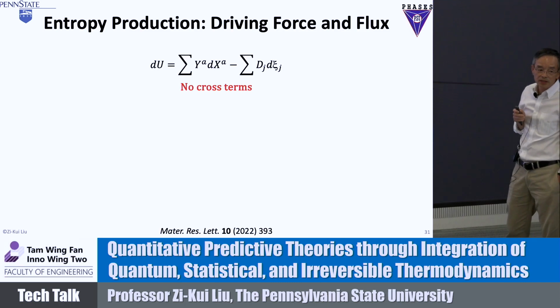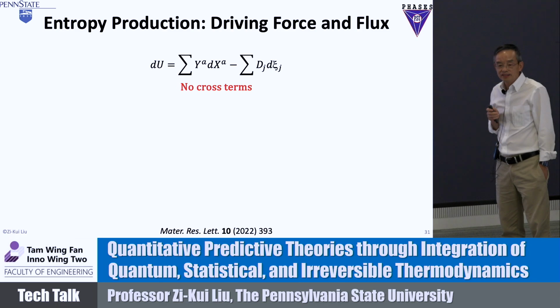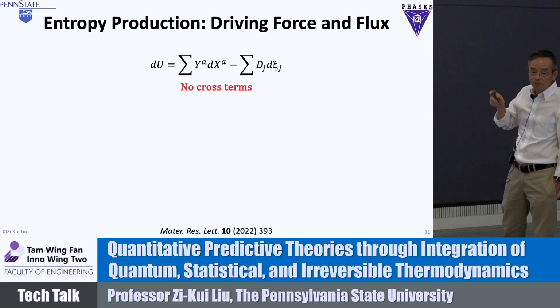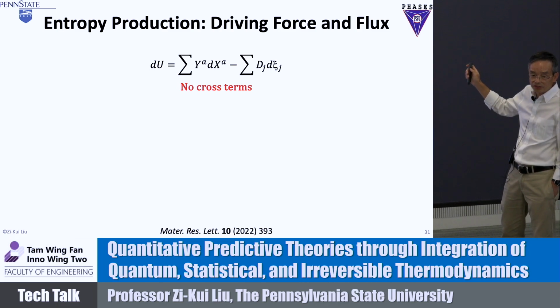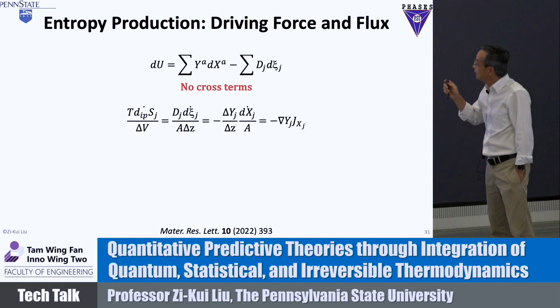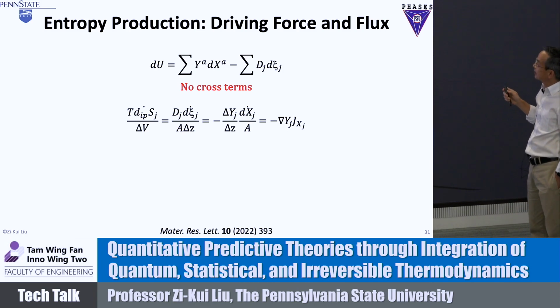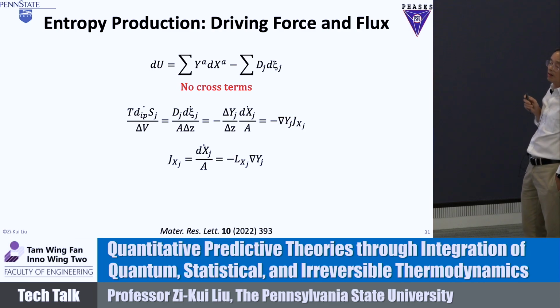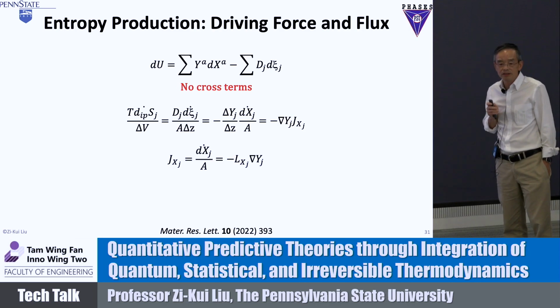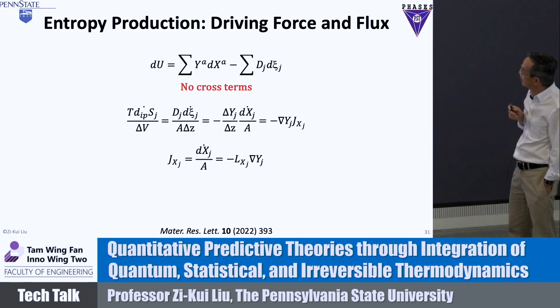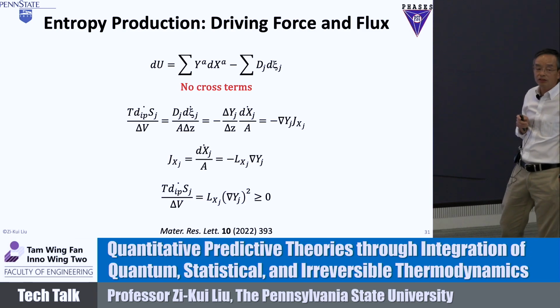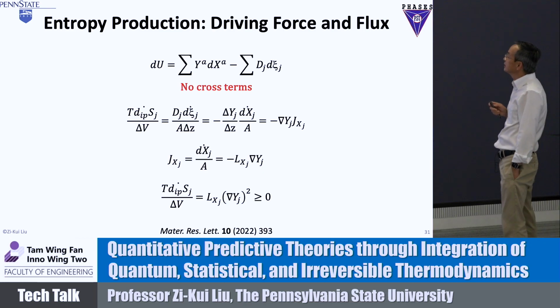There are no cross terms in the combined law. So his cross term is just because his frame of reference changed. That means we can calculate the entropy production of any process. If we define it based on Truesdell's book, then we can calculate it as equal to the delta of the potential times the flux. Then the flux must be only a function of its own gradient, the chemical potential, or the conjugated potential. And then the second law, everything is beautifully fulfilled.